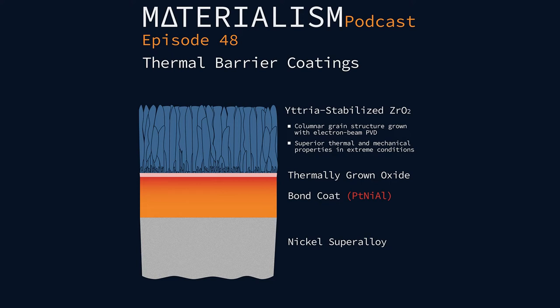Right. And then obviously when you heat this thing up and use it, if you have this bond coat layer with different elements, we know that this is eventually a diffusion couple you've made. And there's a reaction between the bond coat materials and the nickel alloy, and you can see that beneath the bond coat. So we've got the makings of something that a ceramic could adhere to. We have this thermally grown oxide. Now we need to figure out a way to actually put a low thermal conductivity ceramic onto that. How do we do it?